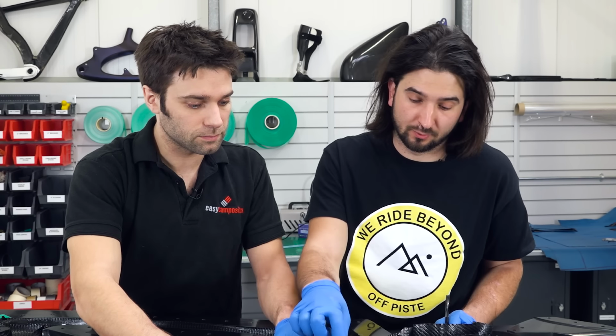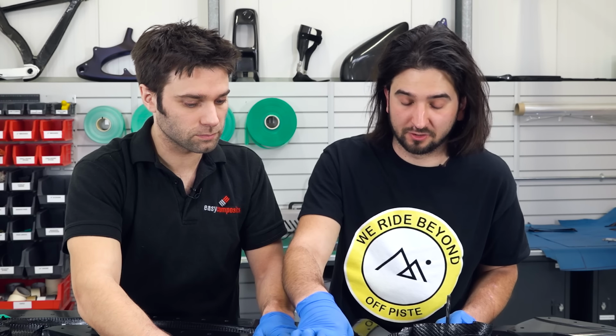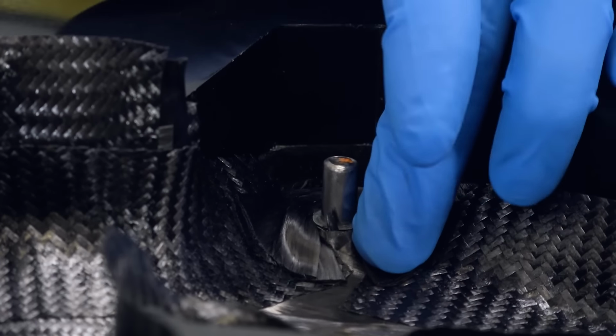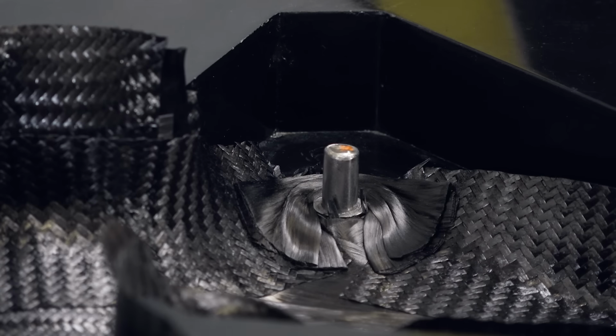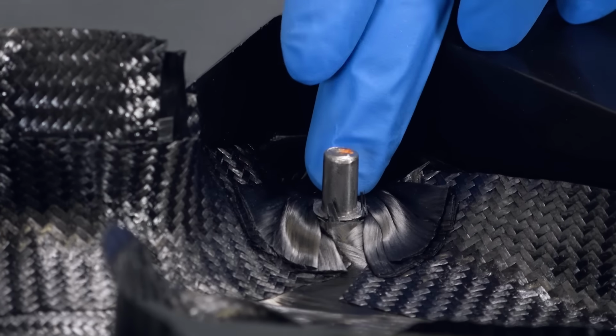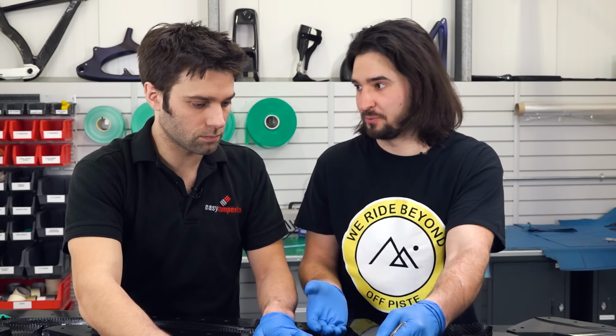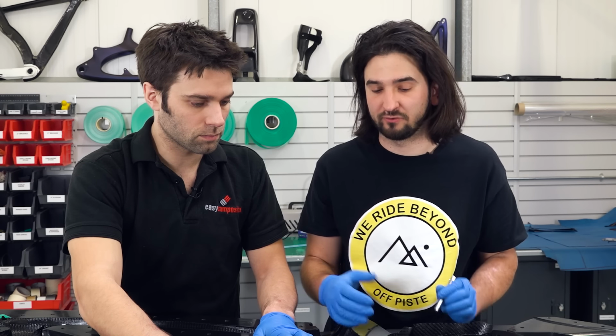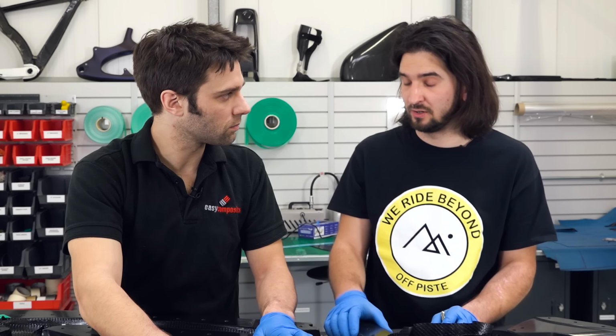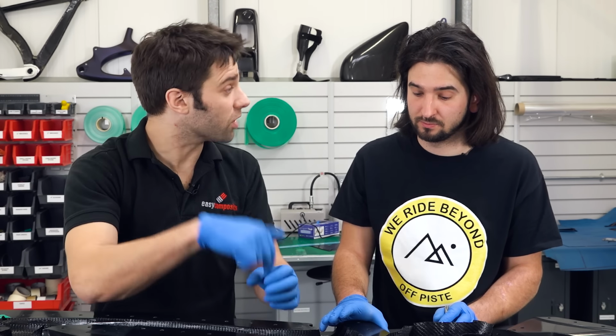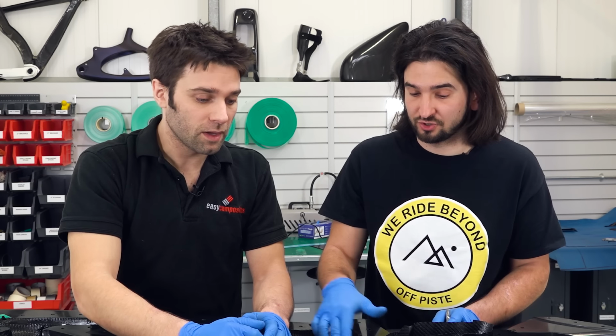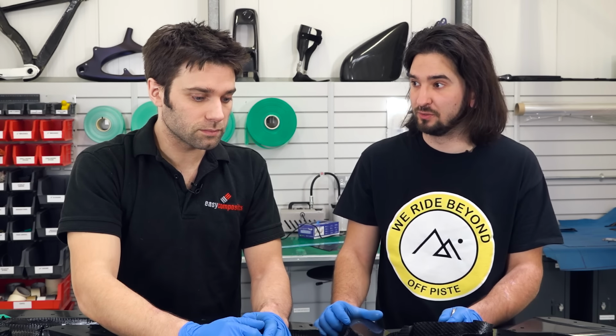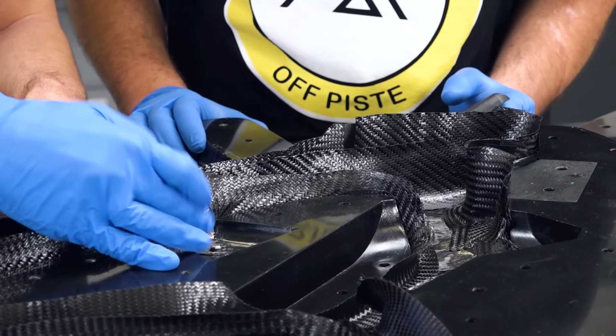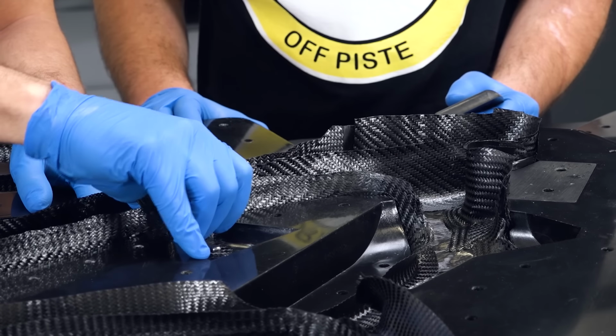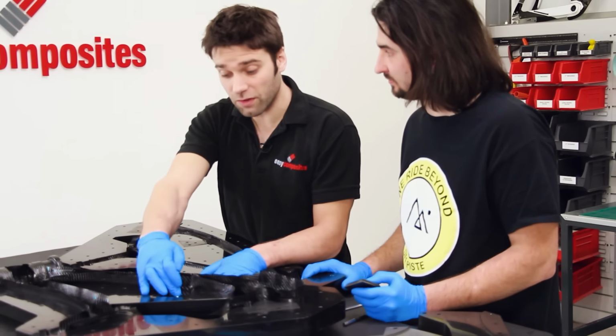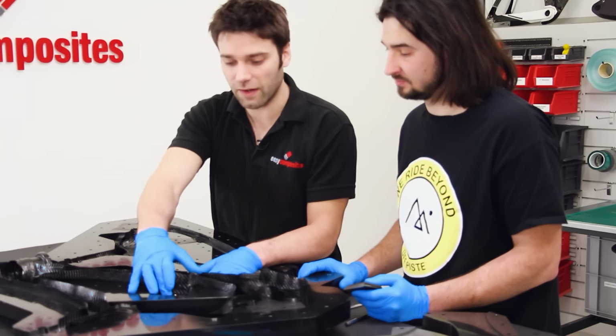So basically, we can see only the top layer here, but underneath the top layer we have unidirectional carbon going around the pin. The reason why I laminate around the pin is because, for example, if you drill the hole, then we have fibers which have effectively been broken by the drill bit. So now all the fibers do what they're supposed to do. This area is completely solid with carbon, so there's not going to be any vacuum bag in there. Presumably it's really critical, the number of layers that you put in that area.